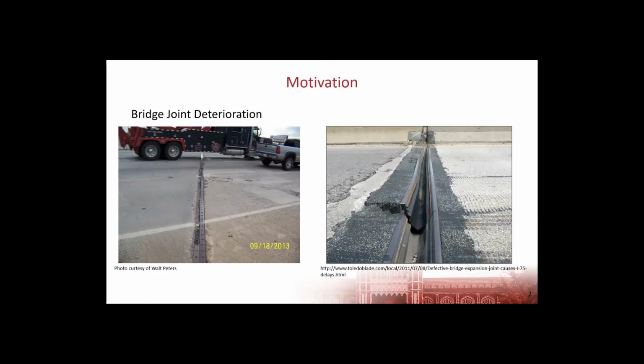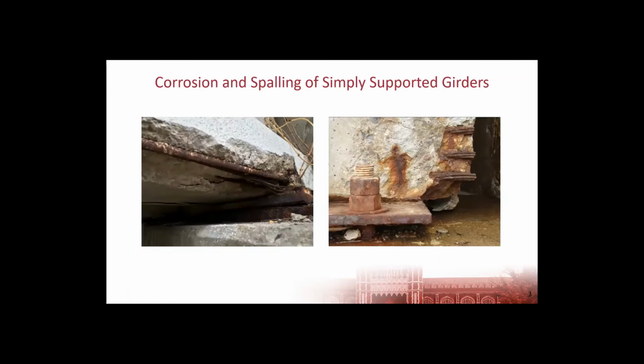Not just fixing those joints is necessary, but as they're damaged, they're letting chloride-permeated water go onto our girder ends within the bridge, and it's causing a lot of damage and corrosion within our precast girder end regions, where we have our major location of pre-stress transfer. We have high shear forces, and we've seen in some testing of full-size girders with this type of corrosion damage that we can even get deterioration of the bearing regions under service load levels. So this can cause some serious issues in terms of the life of our bridges over time.